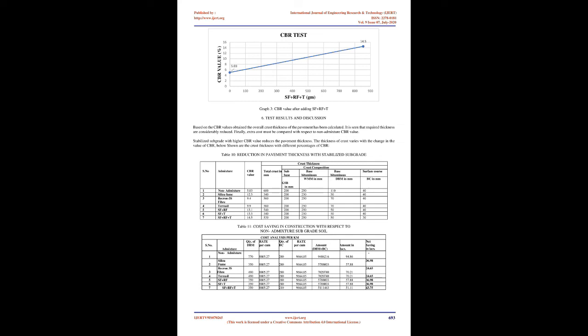After analyzing all the data that is collected or generated, it is found that SF and RF and T is the best combination of admixture for soil stabilization and most economical as compared to the individual admixtures used for soil stabilization. 7 Conclusion. A very important parameter, CBR, California bearing ratio, is used as a tool for determining the improvement of strength of soil in highway construction. CBR is determined with the help of CBR apparatus by adding admixtures, silica fume, Recron fiber, and Terrasil, with various percentages.